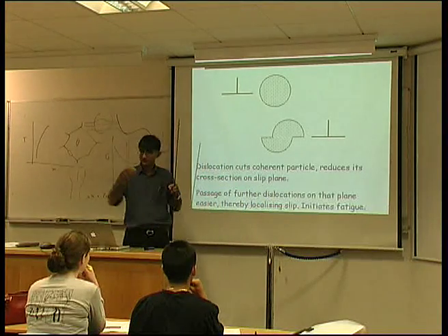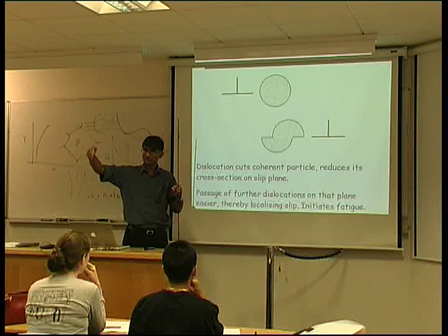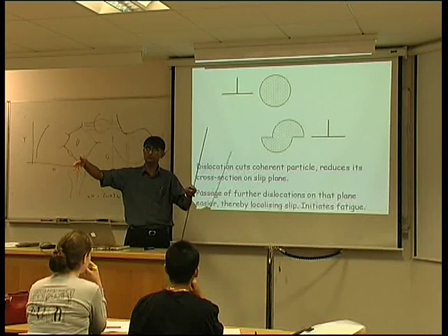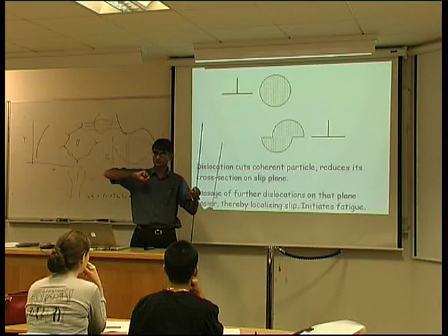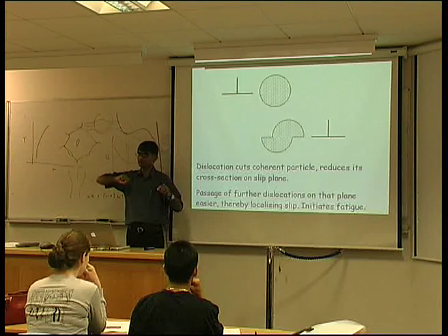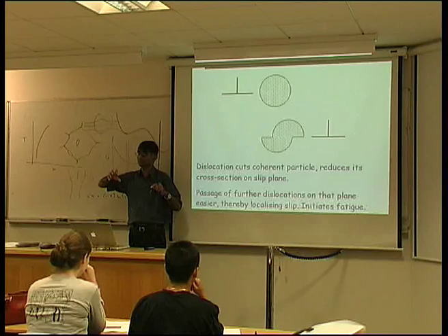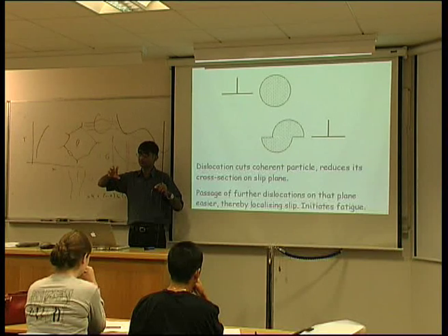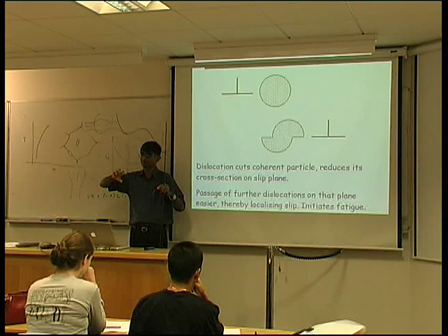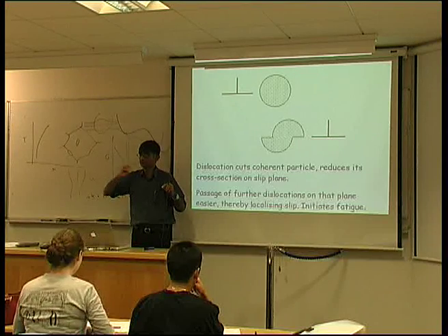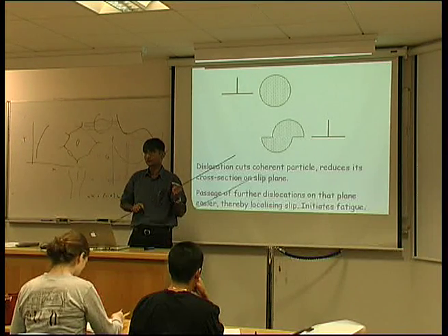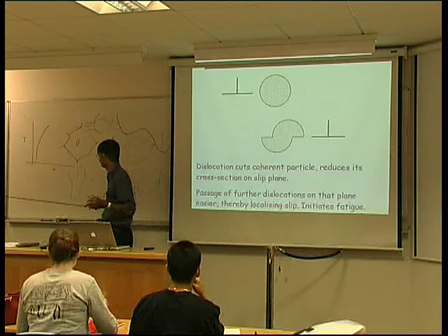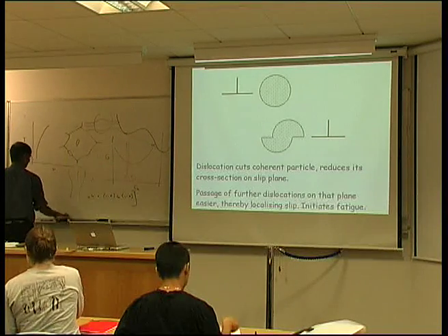And that produces macroscopic slip steps on the surface of your component, which are stress concentrations, and you get fatigue crack initiation. So for fatigue applications, you need to make your precipitates semi-coherent or incoherent. Coherent precipitates are bad news for fatigue. Okay, that finishes today's lecture.